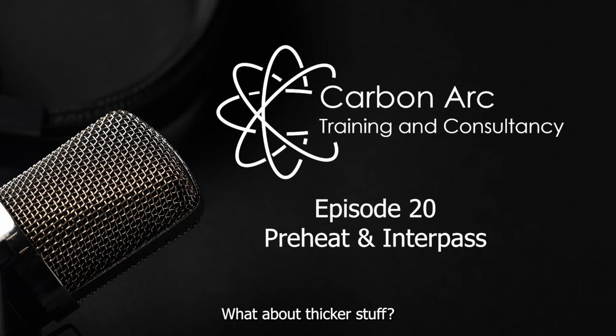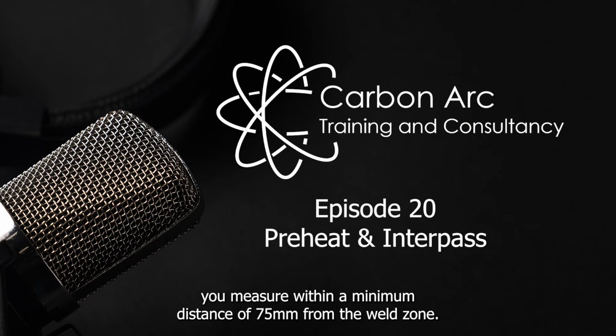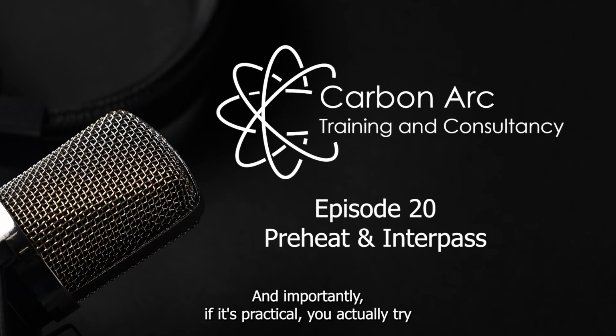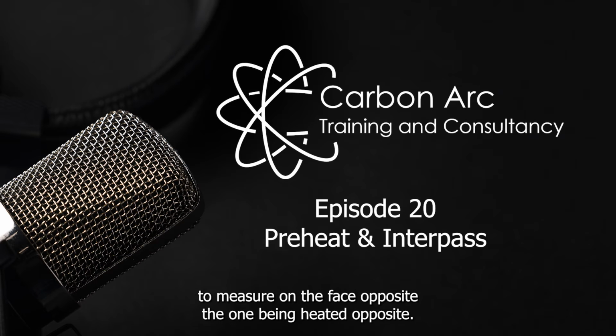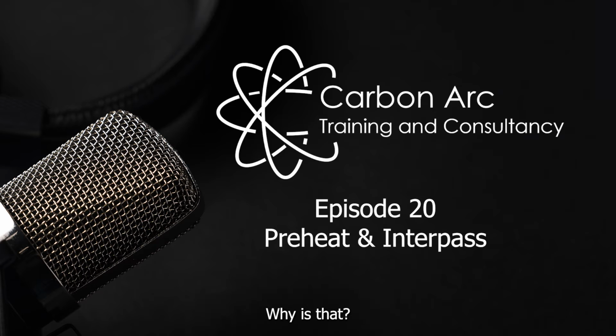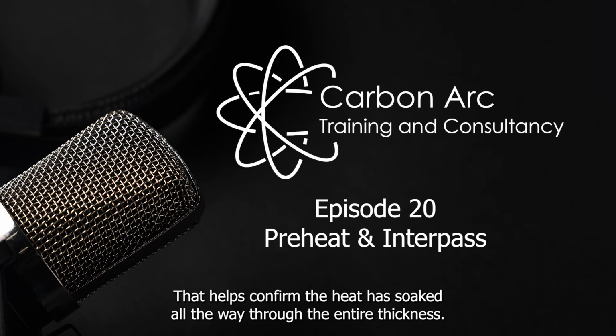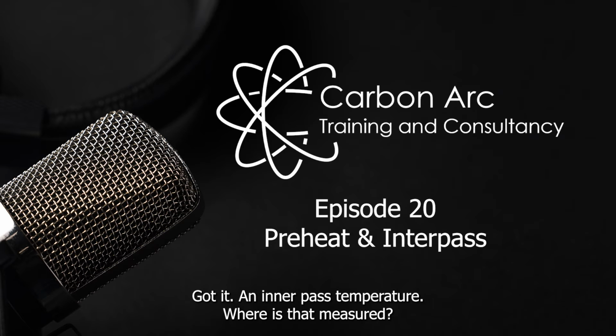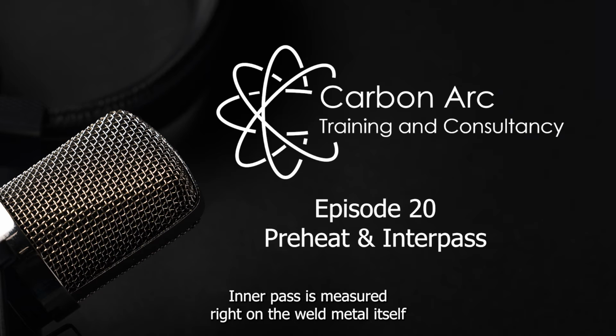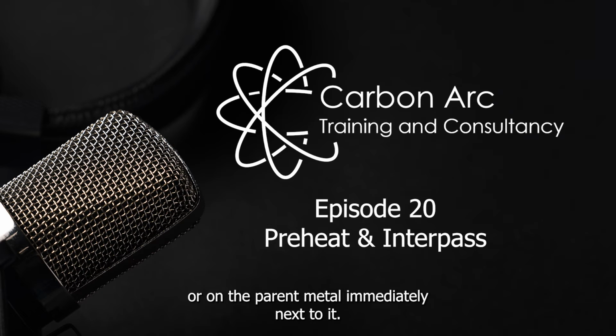Okay, 4T up to 50 millimeter max, on the welder's side. What about thicker stuff? If it's greater than 50 millimeters, you measure within a minimum distance of 75 millimeters from the weld zone. And importantly, if it's practical, you actually try to measure on the face opposite the one being heated. Opposite. Why is that? That helps confirm the heat has soaked all the way through the entire thickness. It's a better check for thick material. Got it. And interpass temperature, where is that measured? Interpass is measured right on the weld metal itself or on the parent metal immediately next to it.